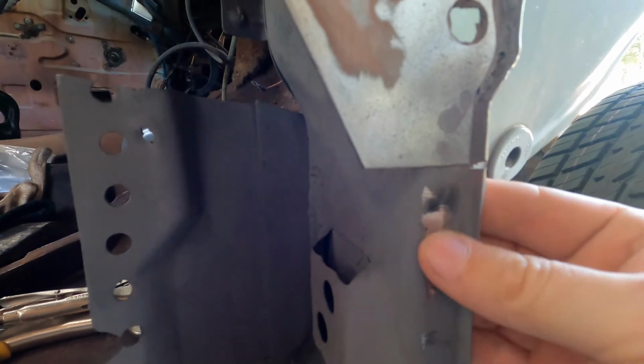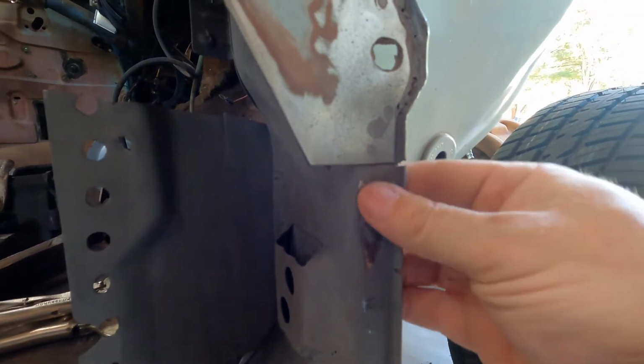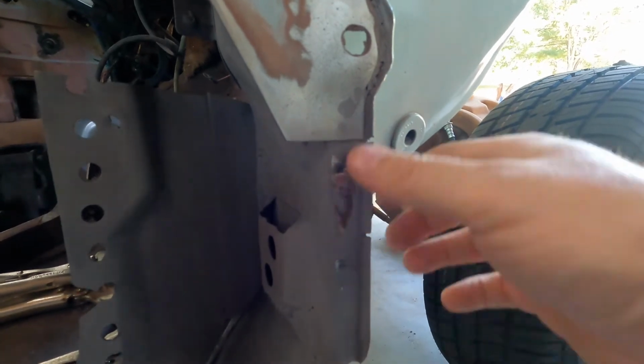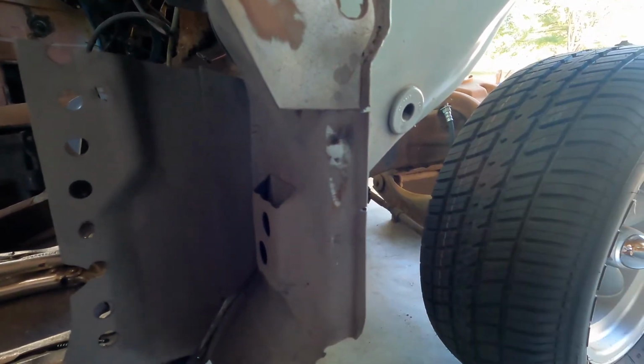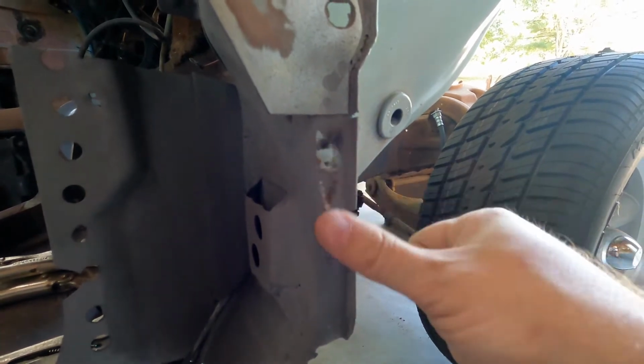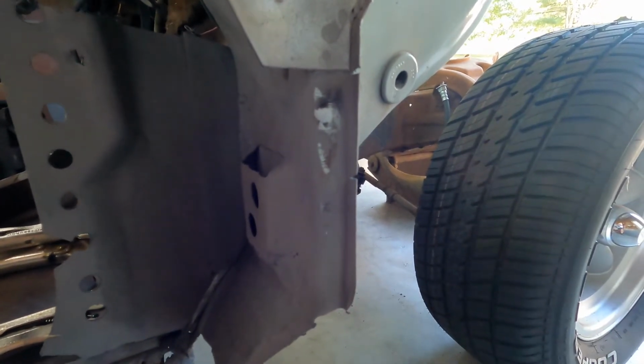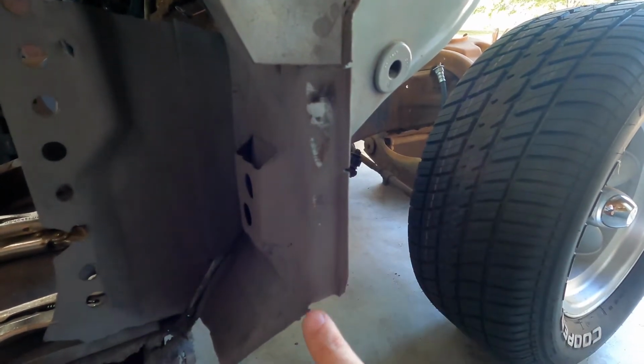It was a little rustier, and I used the MIG welder on that spot because it is a little dirtier, and I sprayed some of this weld through primer beforehand just to keep some spatter down on some of this stuff since I'd already got it cleaned up. But to TIG weld to this side, I'm going to have to strip that off again, because it's weld through for wire welds, which are a little more tolerant for contamination. But even though it's weld through primer, using the TIG welding process, it really wants to be super highly clean, and you don't want to have that stuff on there. So anyway, I'll get the time lapse set back up here and keep getting after it.